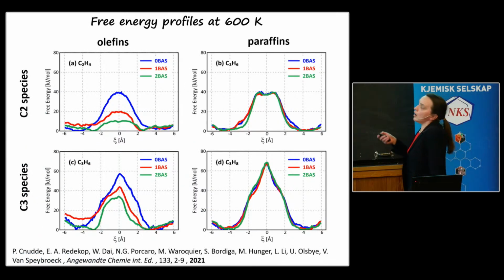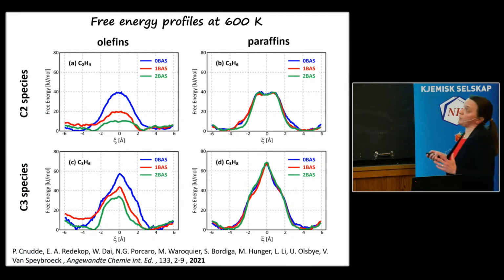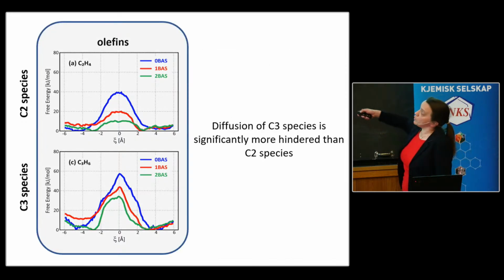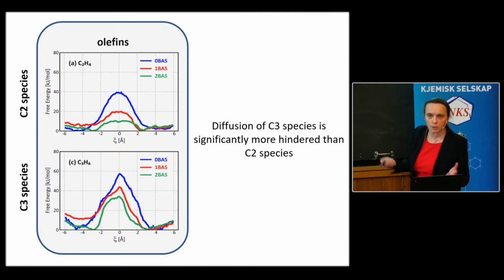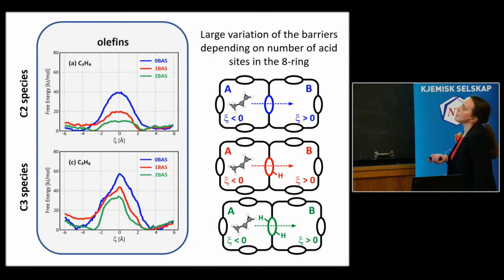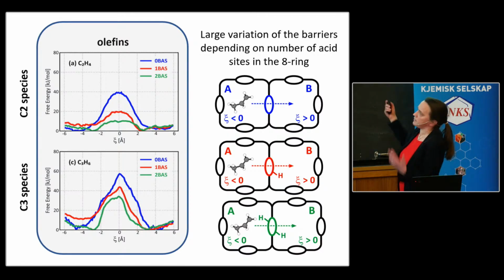These were free energy profiles for a series of components. So here you have olefins, where you have a double bond. Here we have paraffins, we have C2, we have C3 species. If we have no double bonds, then we see no influence on the acidity, let's say. If we have double bonds, we always see an influence. So, of course, propene has more difficulties to go from one side to the other. We can see that the barrier here is higher than, for example, compared to ethene. It's normal, of course. Propene is a bigger molecule. Yeah? But interestingly, irrespective whether it's ethene or propene, we always see that the barriers are lowered when we have acid sites here.